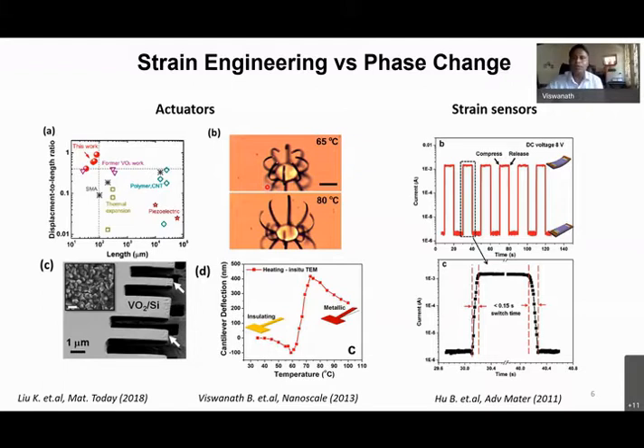There are many applications. I won't be able to cover all of them, including many of the actuators, strain sensors, even phase change based transistors, switching applications, and so on. And if you want to make actuators, in this case, you can see the photograph of how this can be used as a gripper. The structural phase transformation in VO2 goes from monoclinic to tetragonal around 68 degrees Celsius. So clearly you can see during the phase transformation, due to the volume change, it is possible to use them as a gripper, because you will see each and every arm here deform.